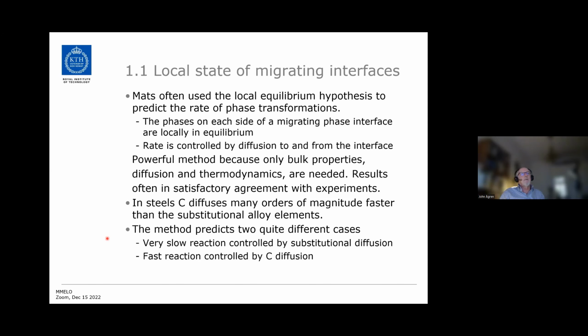Now, this is a very powerful method because it only needs bulk properties which can be measured independently. You don't need to know anything about the phase interface. And moreover, the results are often in satisfactory agreement with experimental data. When you apply this to steels, carbon diffuses many, many orders of magnitude faster than the substitutional elements. And that means that the method predicts two quite different cases, either a very slow reaction controlled by substitutional diffusion, or a quite fast reaction controlled by carbon diffusion.